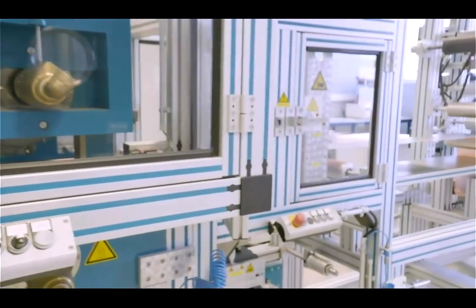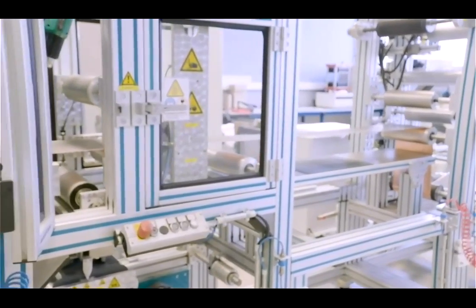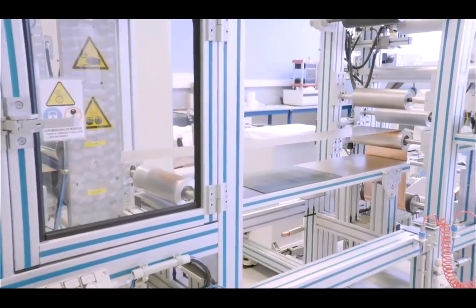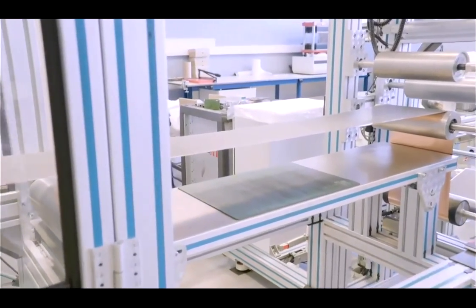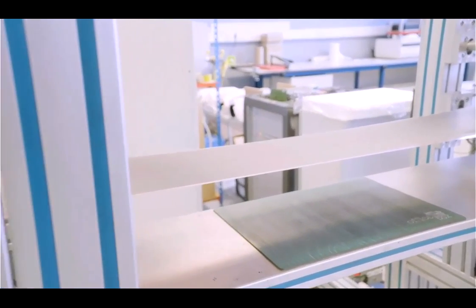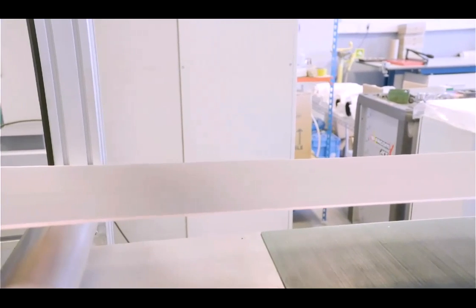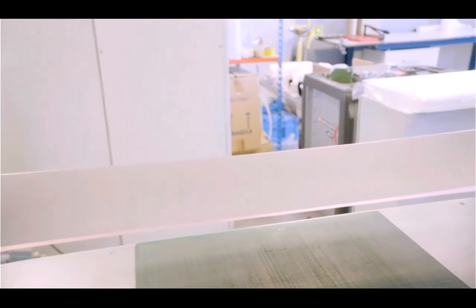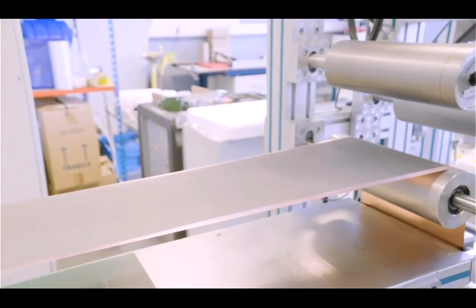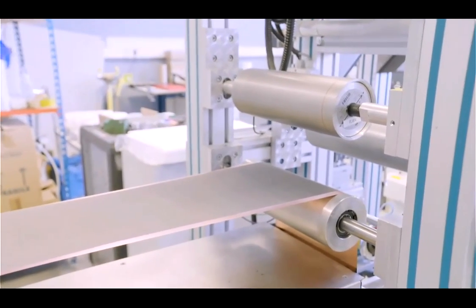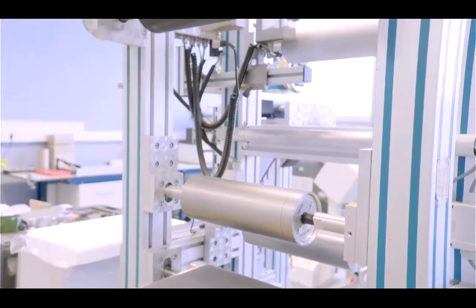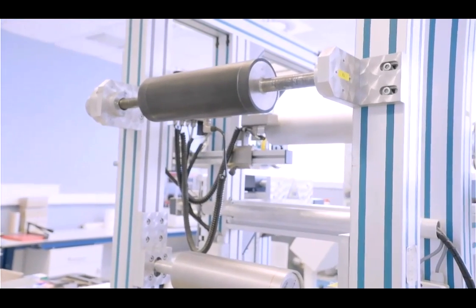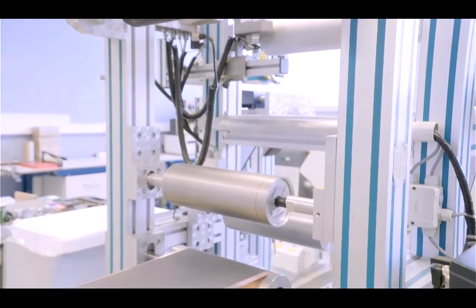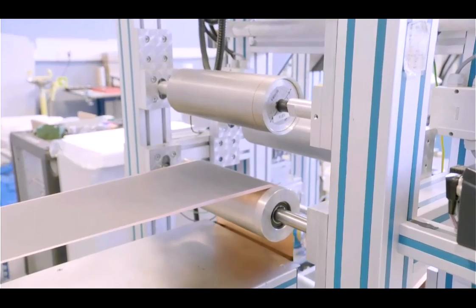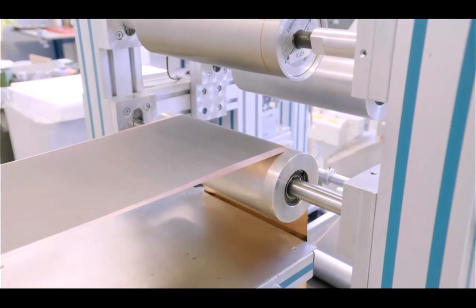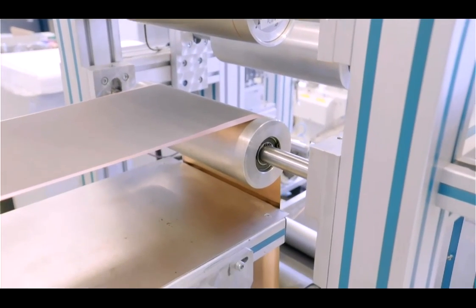Okay, so let me talk a little bit about the process parameters. With this coater, we have the possibility to coat between 0.5 and 5 meters per minute. But our usual coating speed is 1 meter per minute because we are limited by the length of the oven. The maximum coating width that we can do is 275 millimeters because the width of the rolls is 300 millimeters. Sorry. So about the ovens, we can increase the temperature from 50 degrees up to 180 degrees.